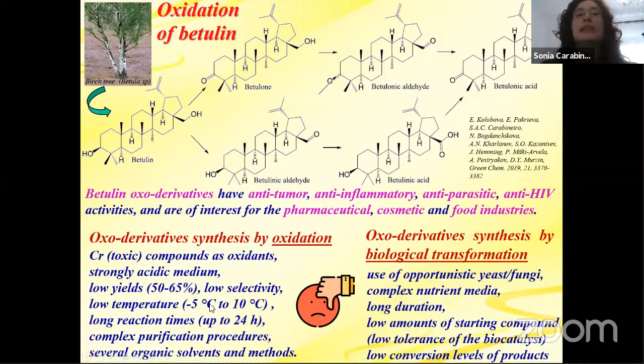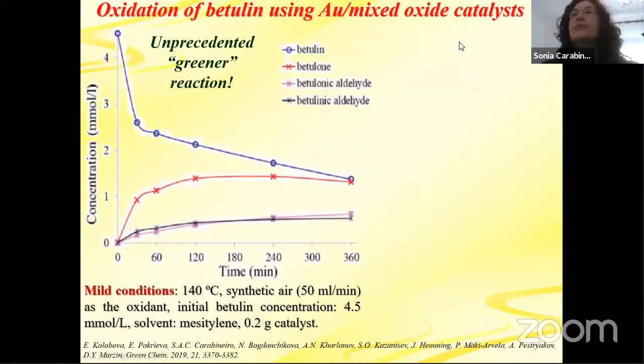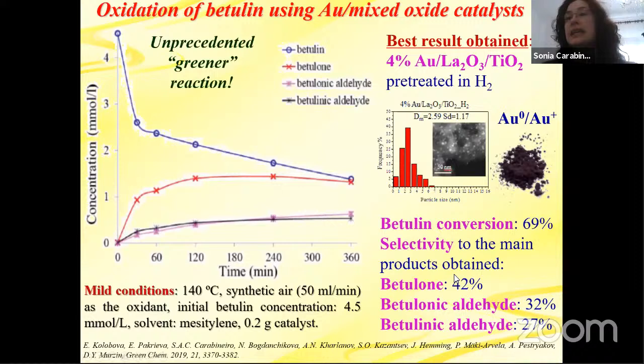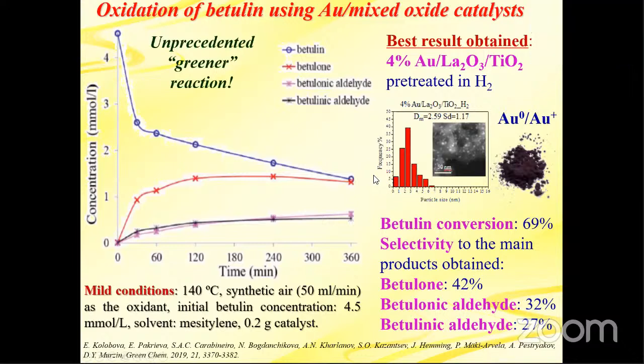And we see here, at relatively mild conditions, 140 degrees Celsius, synthetic air as the oxidant. And the best result was with this catalyst, this mixed catalyst. And we obtained a betulin conversion of 69% and this selectivity to these main products. So it was a good result.